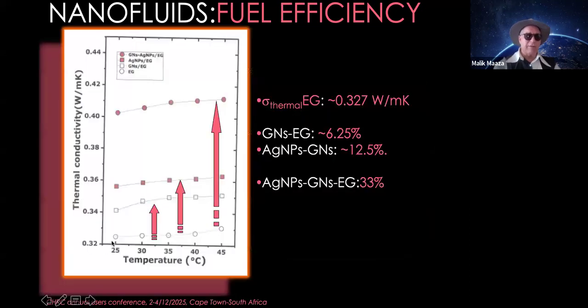And the thermoconductivity of it, here with ethylene glycol as a host material, you can see is around 0.33 watt per meter per Kelvin. But when you use silver anchoring graphene sheets, the thermoconductivity jumps by 33%. You would say, oh, it's just moving from 0.33 to 0.40. It's not much. No, you are wrong to think like that.